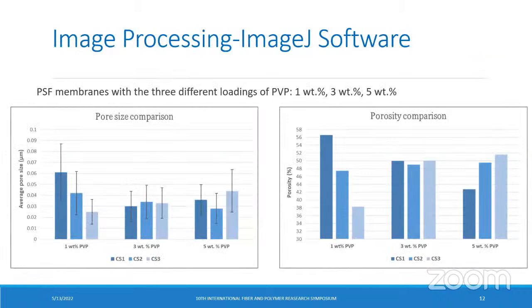Actually, when we analyze these kinds of images, it gives us these results. And also when we worked on some mechanical properties analysis using DMA, we started to see that the mechanical properties are consistent with what we have found in terms of the pore size and porosity measurement.